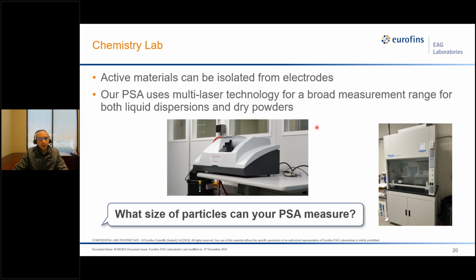The next piece of equipment we have in-house is a particle size analyzer. This particle size analyzer is equipped with multi-laser technology, and you can measure a broad range of particle sizes. Of course, people ask what particle size we can measure. It can measure in dry mode, which is just putting a powder inside, or in the dispersion mode, the wet mode. In dry mode, it can measure from about 100 nanometers to 2.5 millimeters. For the liquid dispersion mode, it can measure from 40 nanometers to also 2.5 millimeters.